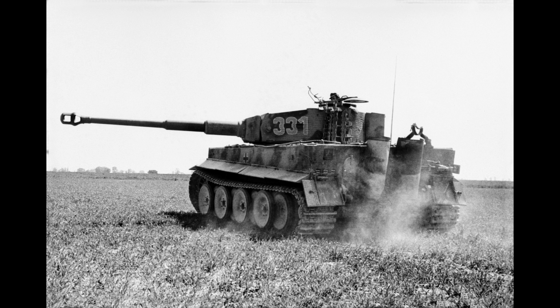Another refinement addressed the armor backing the ammunition storage bins inside the hull. Fire from penetrating hits remained the leading cause of catastrophic tank loss, the secondary explosion of stored ammunition killing crews and completely destroying vehicles. Engineers developed supplementary armor panels with specialized compositions that resisted spalling when struck, reducing the shower of fragments that could detonate stored rounds even when primary armor wasn't fully penetrated. These incremental improvements, each addressing specific vulnerabilities identified through combat experience, represented exactly the kind of continuous refinement that German industry could no longer accomplish.